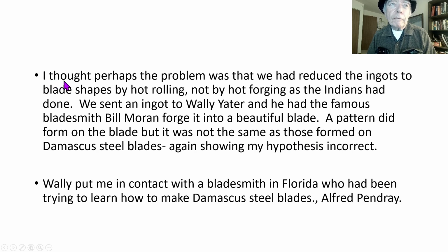So I thought at first that perhaps the problem was that we had reduced ingots to blade shapes by hot rolling, not forging, as the Indians had done. We sent an ingot to Wally Yater, a bladesmith out east, and he had the famous bladesmith Bill Moran forge it to a blade. It was a beautiful little blade. It had a pattern on the surface. It was not nearly the same, and the internal microstructure wasn't the same.